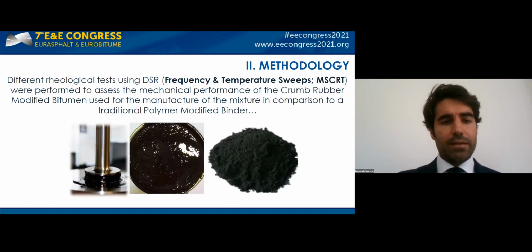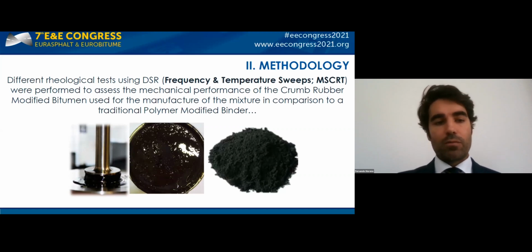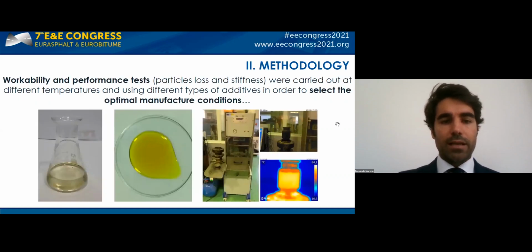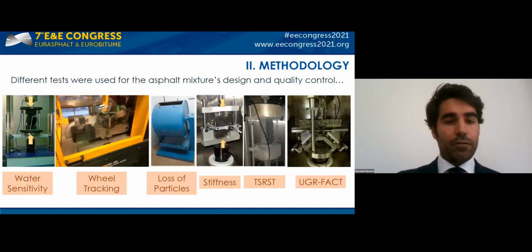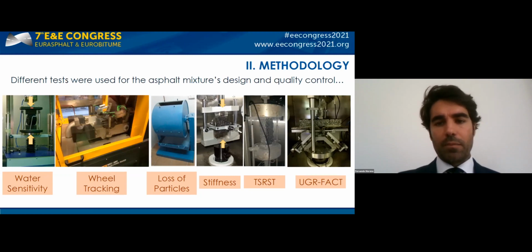During the design of this material, different rheological tests using DSR were performed to assess the mechanical performance of the crumb rubber modified bitumen used for the manufacture of the mixture, in comparison to a traditional polymer modified binder. Workability and performance tests were carried out at different temperatures and using different types of additive in order to select the optimal manufacture condition. After that, different tests were used for the asphalt mixture design and quality control.